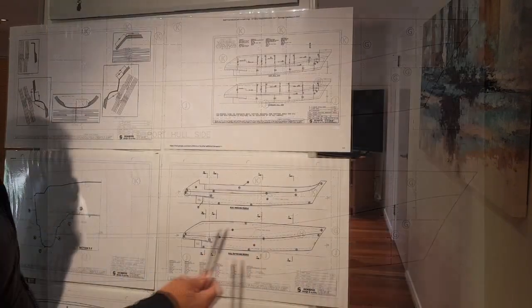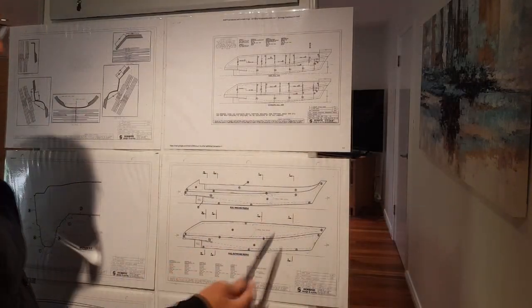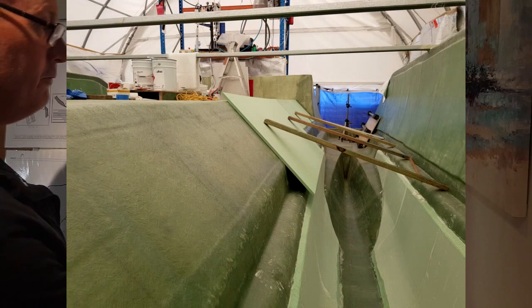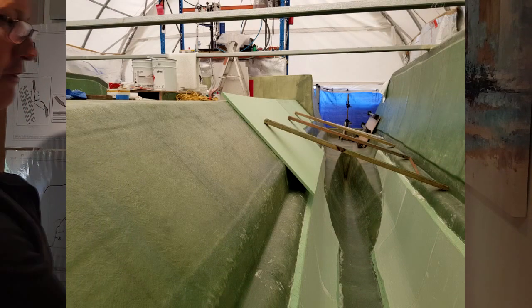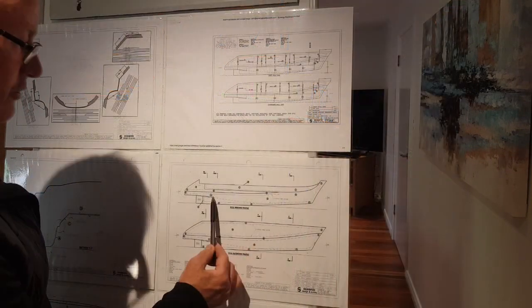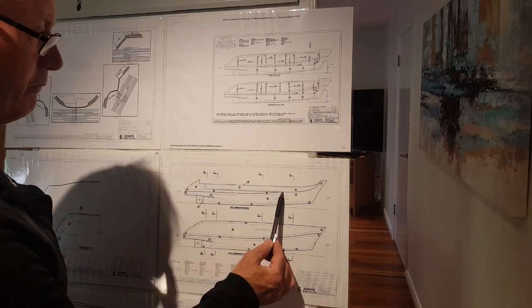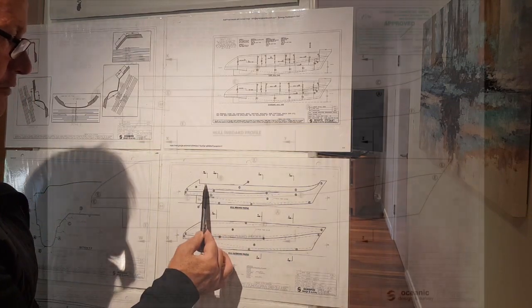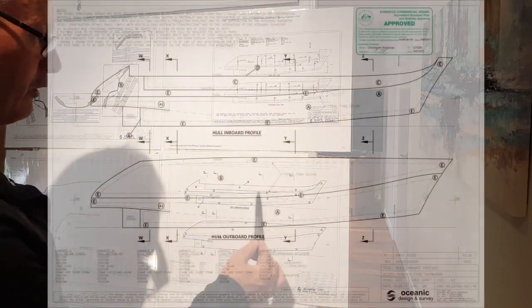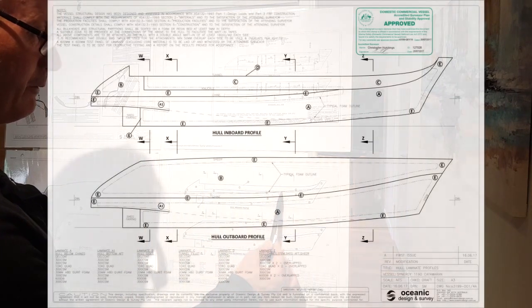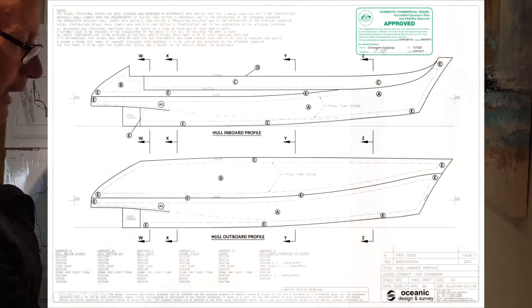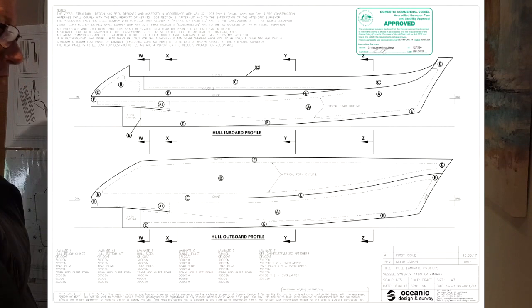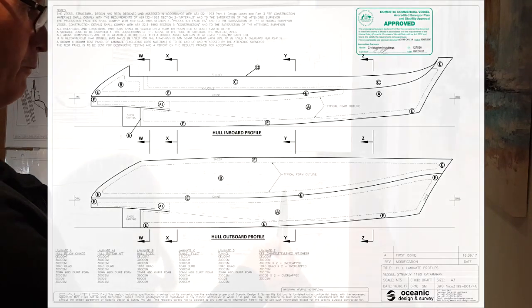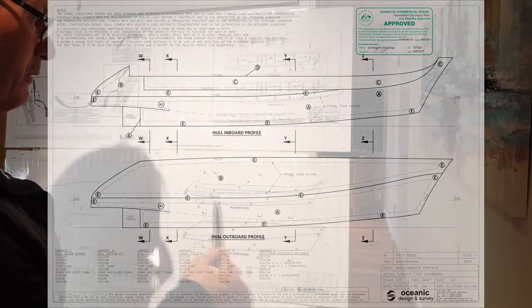And then in respect of the inner panels, i.e. the chamfer panel, the inner hull, or the tunnel hull, you can see in fact that the hull form foam actually starts here down at the stern, comes along, then joins around about here, about where the knuckle is, and then goes back along to the stern again. Now this is 20mm foam at the top, blending into 30mm foam at the bottom.